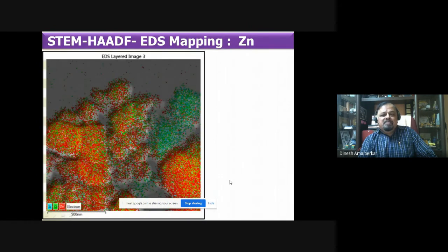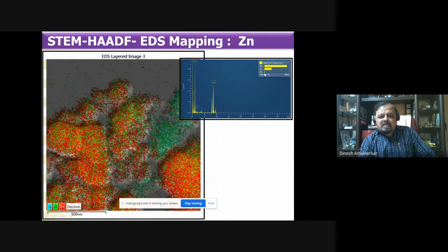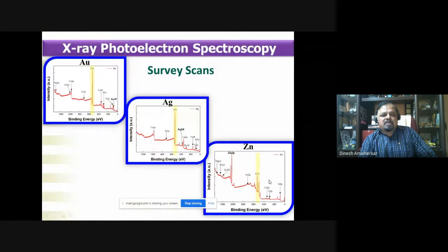So zinc oxide everywhere except this patch, which tells you that it must be silica. And when we have done the EDAX analysis, this is in order. Zinc is more, oxygen less, and this is expected in case of zinc oxide based Jasadbhasma. Okay, the most surprising result in the X-ray photoelectron spectroscopy, when you have taken the survey scans of all Swarnabhasma, then Roupyabhasma and Jasadbhasma, what we could see here, this is the survey scan, the oxygen O1s peak is much more intense in Swarnabhasma and Roupyabhasma.